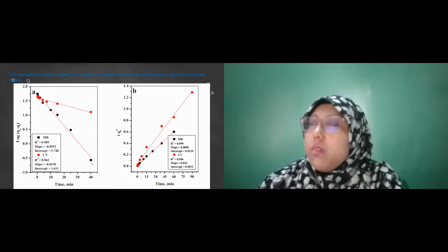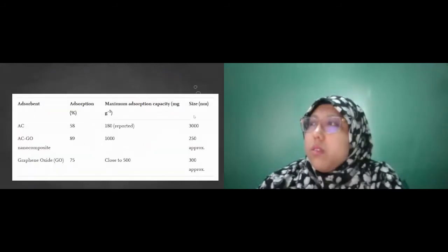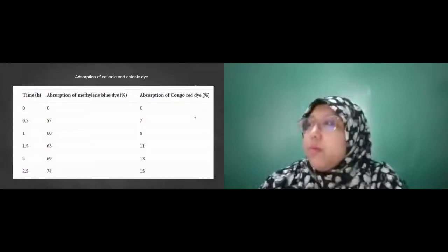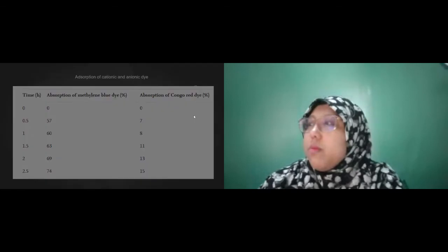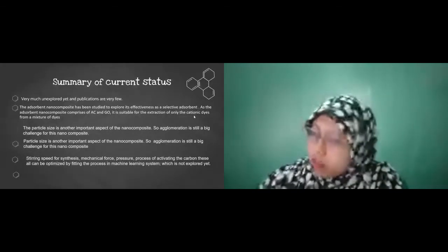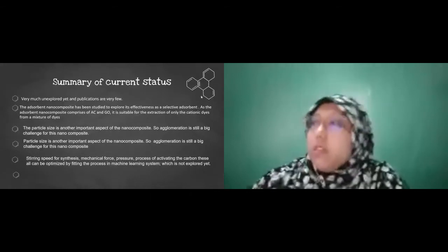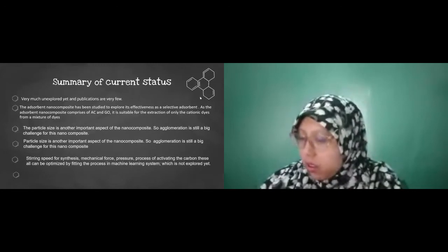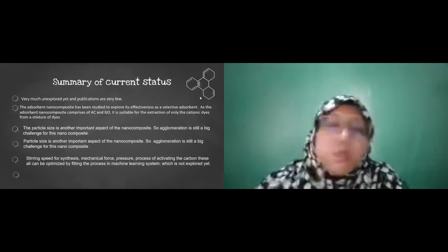Another literature has proposed direct mixing too, and they also received a very good result on this graphene oxide and activated carbon composite. Here you can see they reached a maximum of 1000 adsorption capacity, but they found that it does well for cationic dye and not for anionic dye. One reason can be that whenever graphene and activated carbon are mixed together, the surface area actually decreases. When it decreases, maybe the functional groups first attack the dye or the pollutant, then by electrostatic charge the base becomes charged, and that's how the dye later falls on the carbon surface. So that can be the reason.